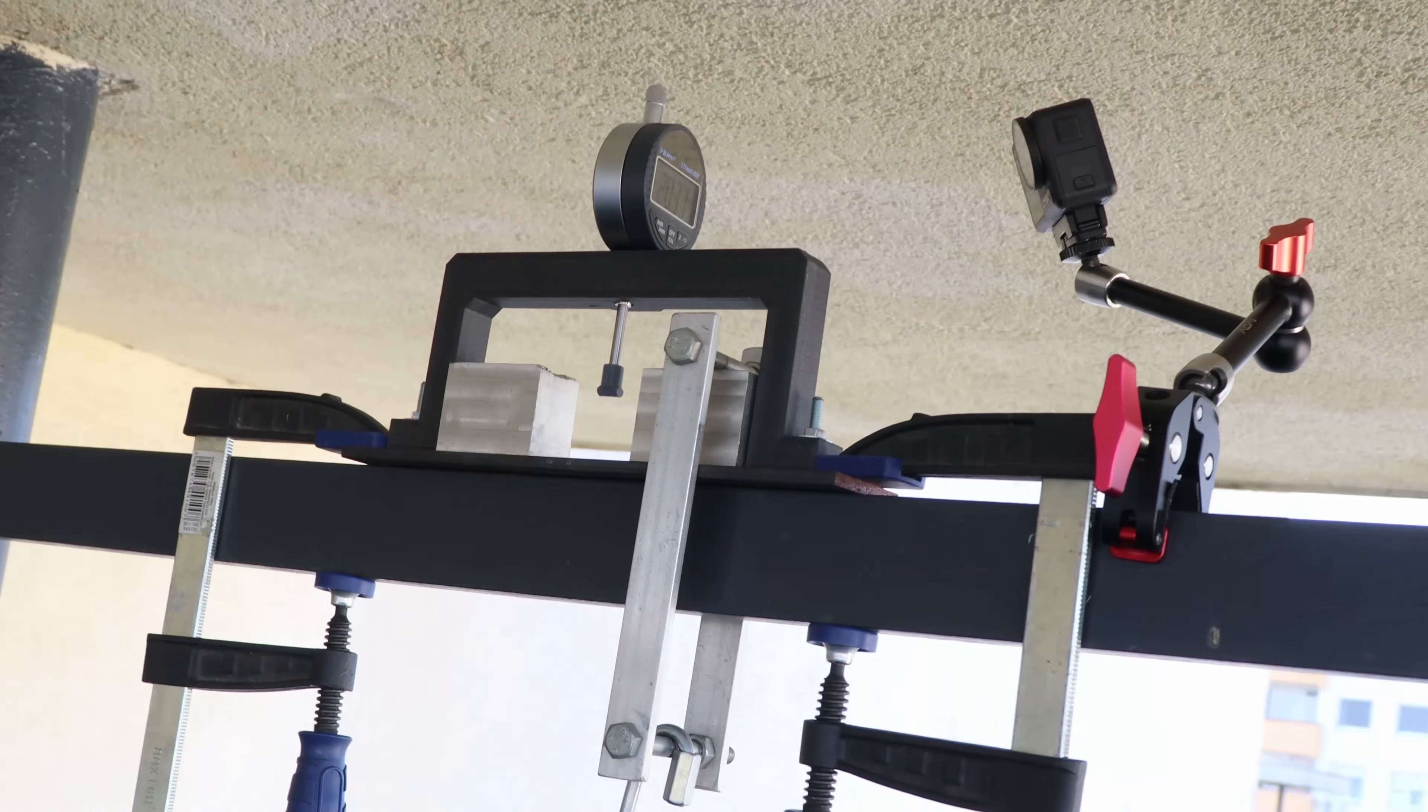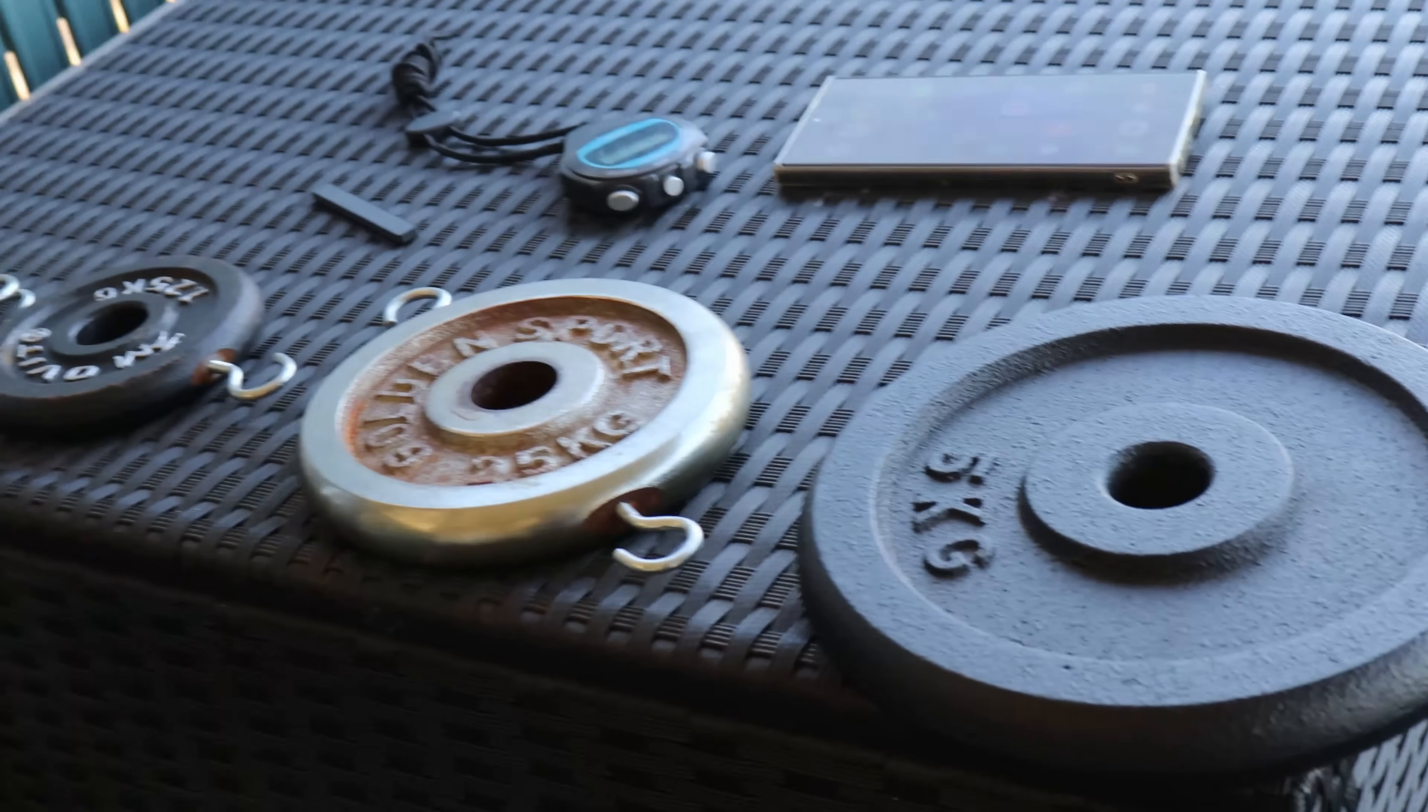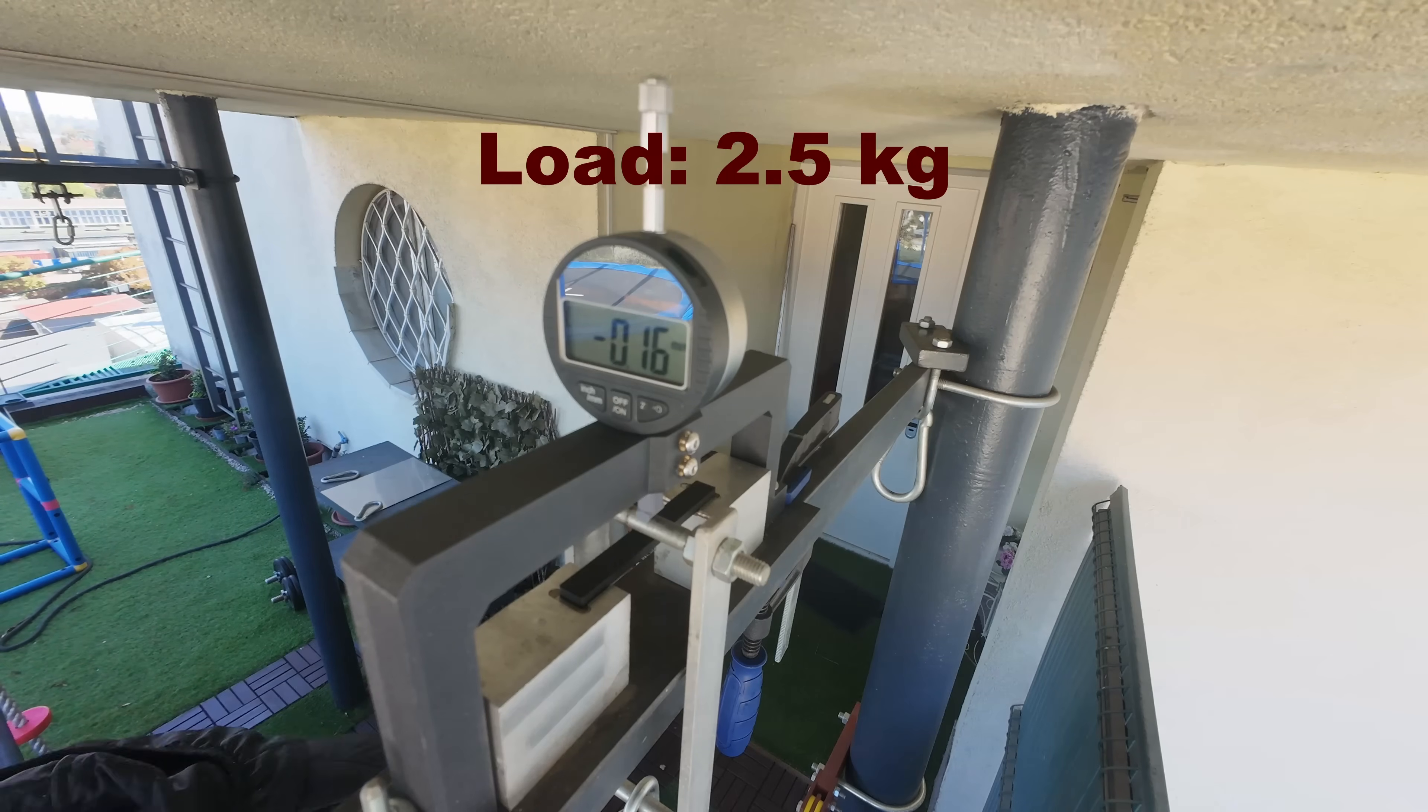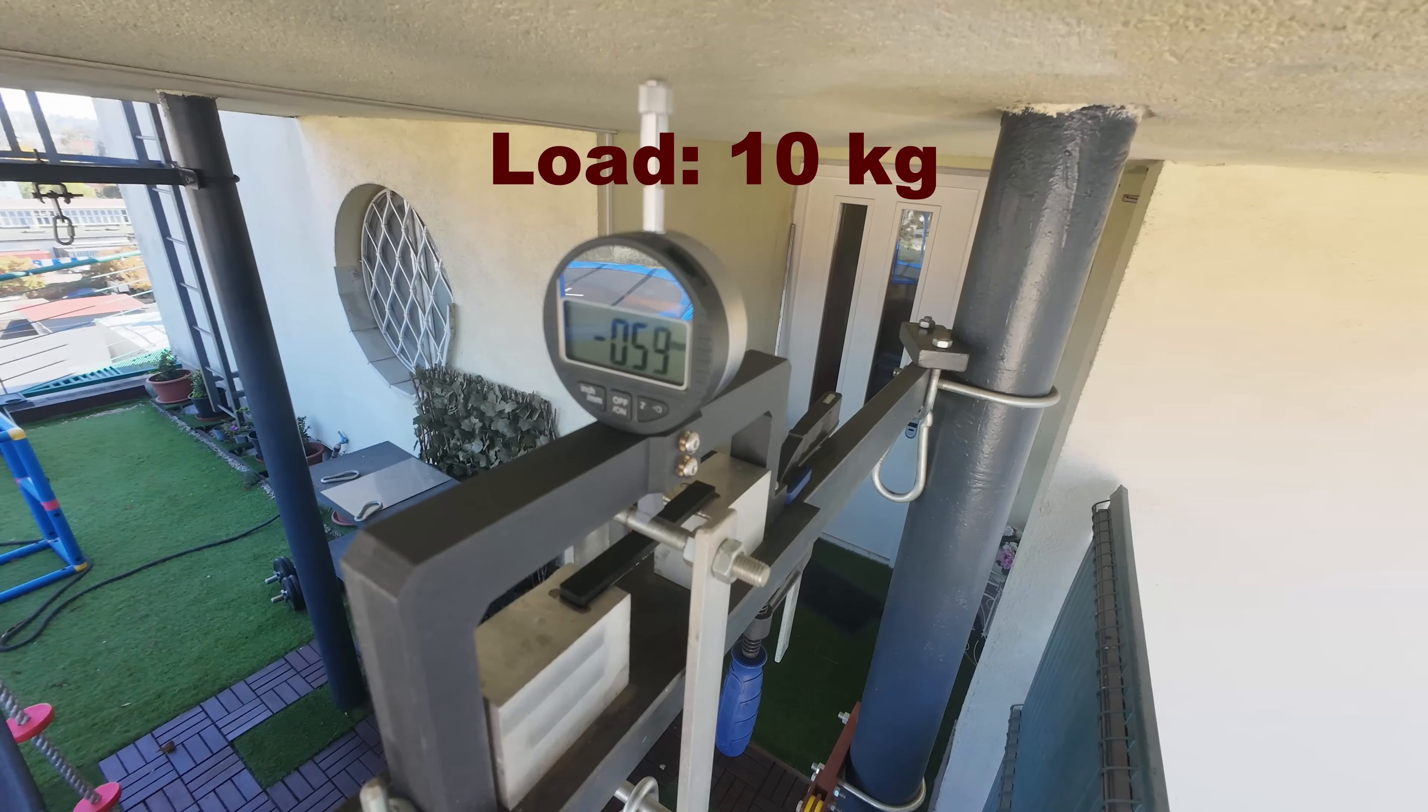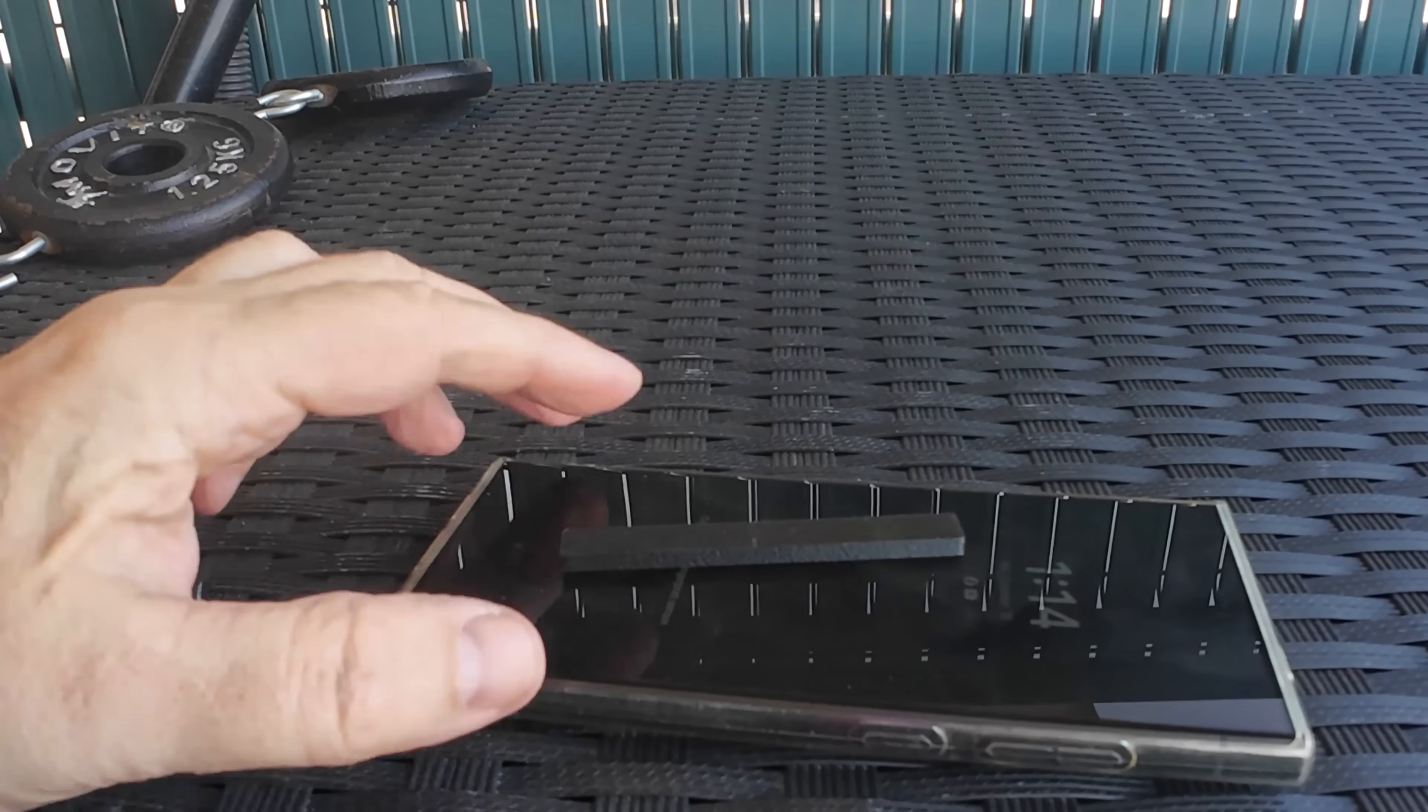And now 3 point bending test to see how stiff is this material. And these are the loads which I replace one by one and I will measure the deformation after 1, 30 and 60 seconds. This is a sped up timelapse video, the load is 1.25 kg, 2.5, 5 and pay attention, no change during the time under constant load. This is 10 kg and no changes at all, very stiff material with very minimal deformation. And immediately after I remove the load it gets back the original shape, no problem with the deformation at all.